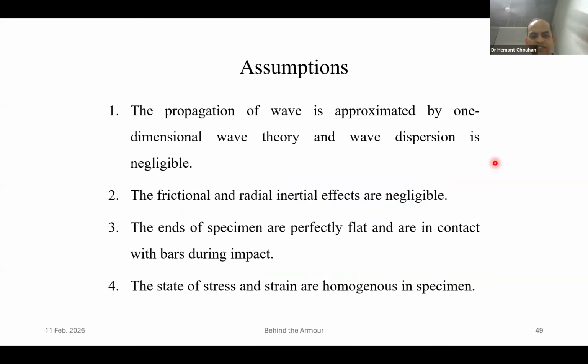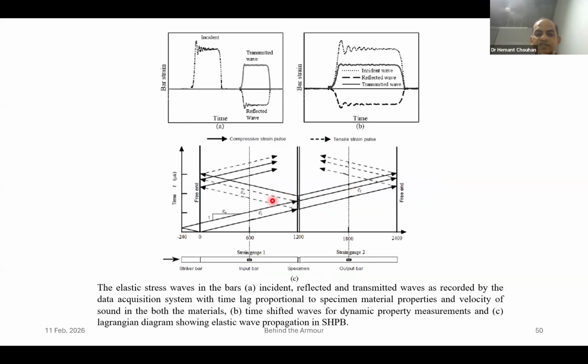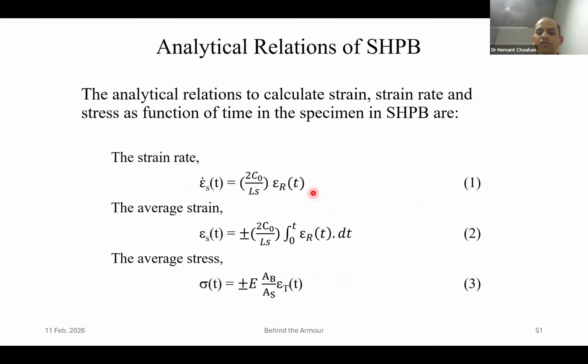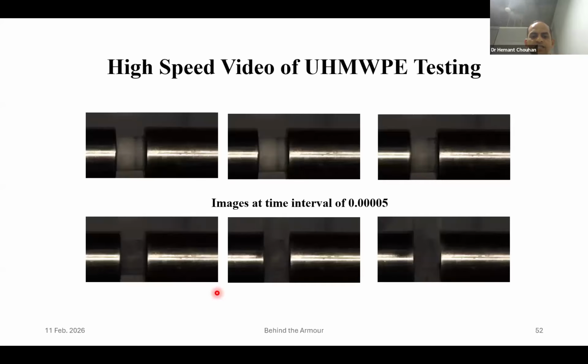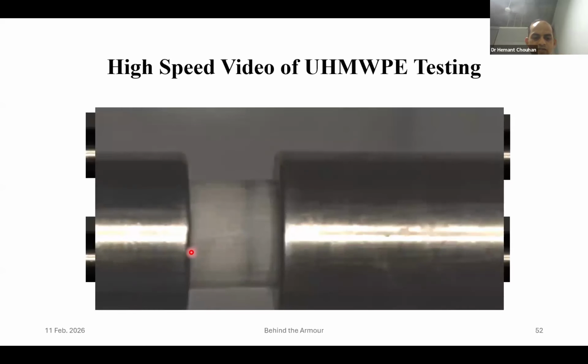And for that, we have some assumptions that everything is in place and correct, because we are not doing things in a three-dimensional world, but in a 1D phenomenon. So if this is the case, then this is my incident energy, a reflected one and a transmitted one. We superimpose them and, using a mathematical formulation, since this is strain gauge data, it has to be suitably converted. We can measure the strain rate, average value of strain and stresses. So that way we can characterize the material at high rates of loading. And this is how the event goes.